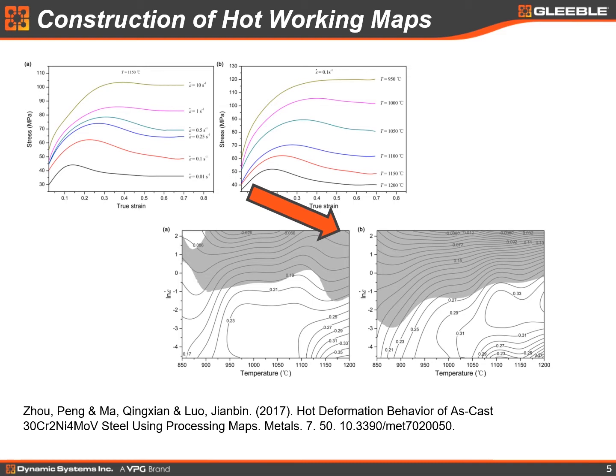So shown here is an example of some work that's been done on a Gleeble to generate these so-called hot working or processing maps for specific alloys, in this case a high alloy steel. Multiple compression tests are run across several strain rates, temperatures, and final strains, and based on the stress-strain response, a workability map is generated. This diagram shows which regions will result in cracking and non-uniform flow, which you don't want to be operating in your steel mill, as well as the strain rate and temperature regions where the material can be hot worked with no issues. These hot working diagrams are a very useful graphical representation, I feel, to visualize the complex mechanisms at play during uniaxial compression and hot working. They're invaluable to understanding how best to create parts through hot working.